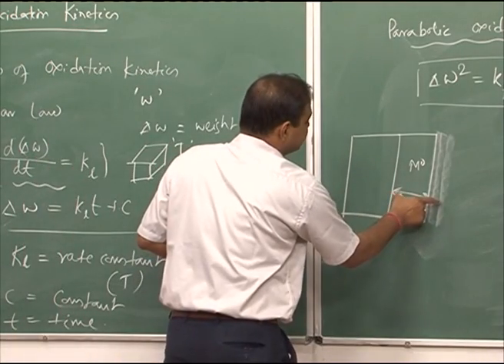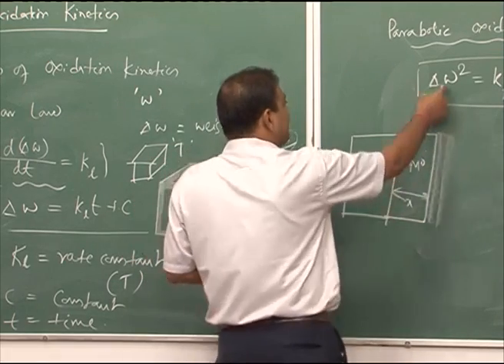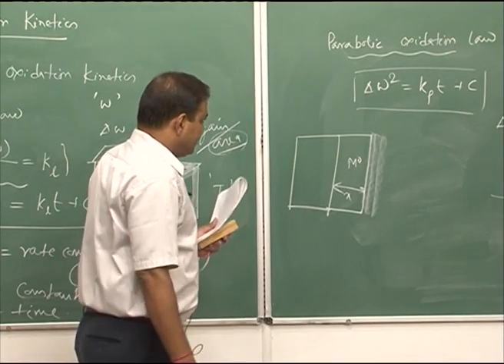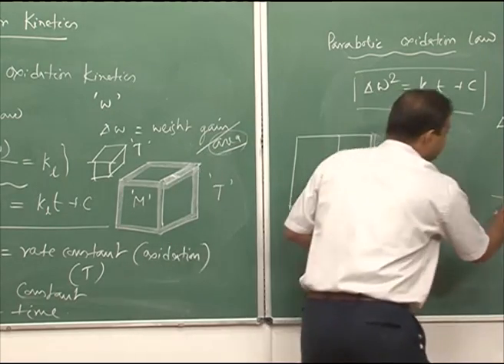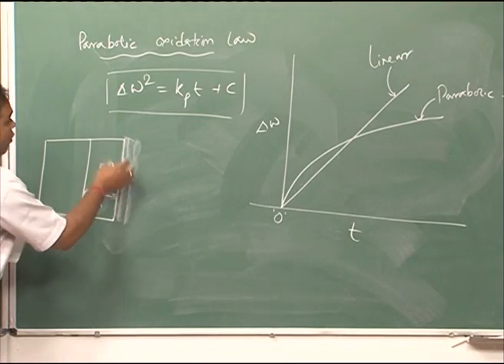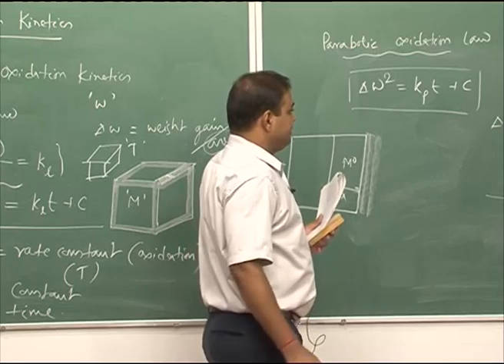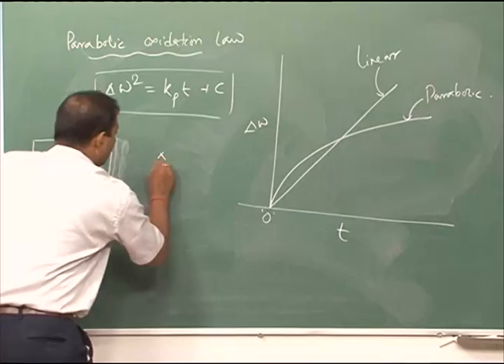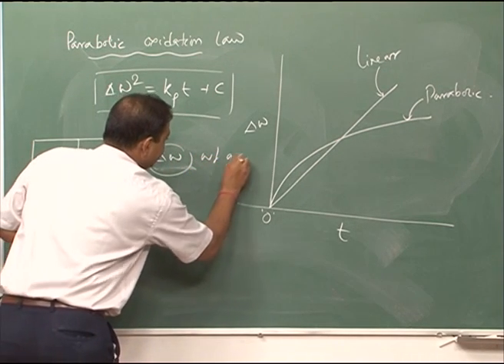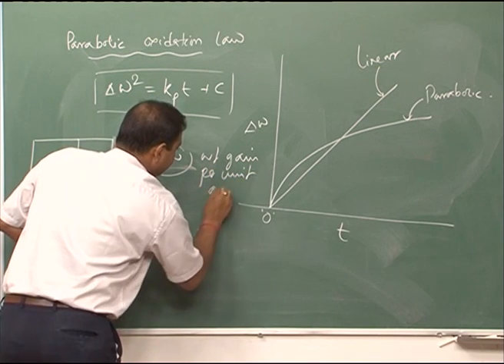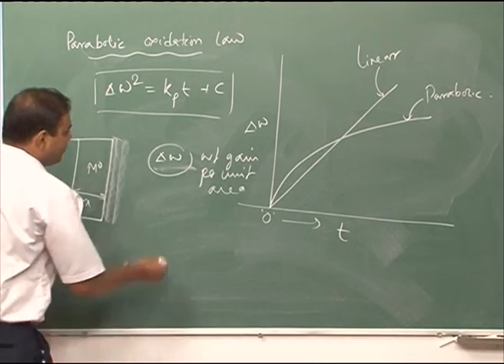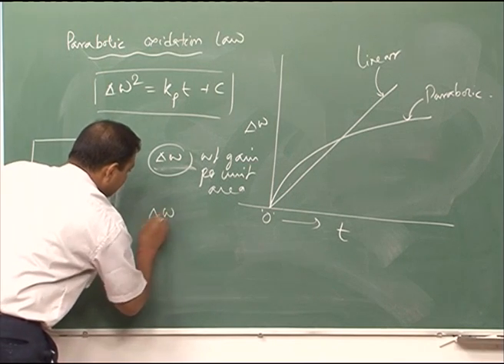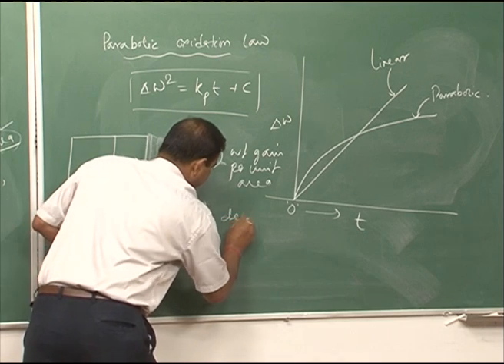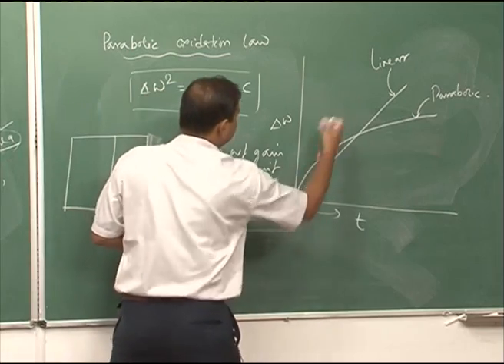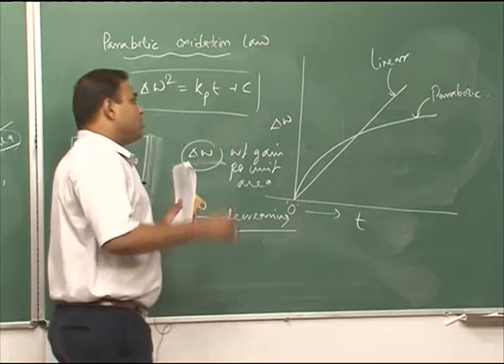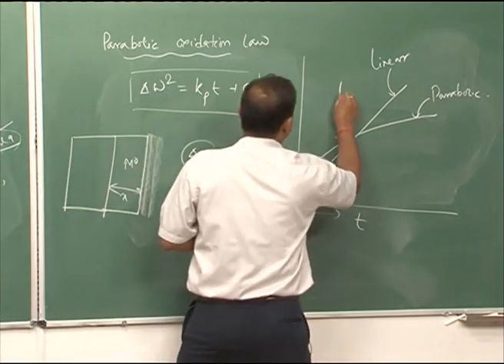If the thickness of the oxide is increasing, that means the weight gain is also increasing. Now, from this point, if the rate of oxidation is taking place, we can see the weight gain per unit area as the time is passing. So, as the time increases, del W by t would be decreasing. That means initially it would be a very fast rate of weight gain, and later on the rate of weight gain would decrease. Now, this is also happening at a particular temperature T.